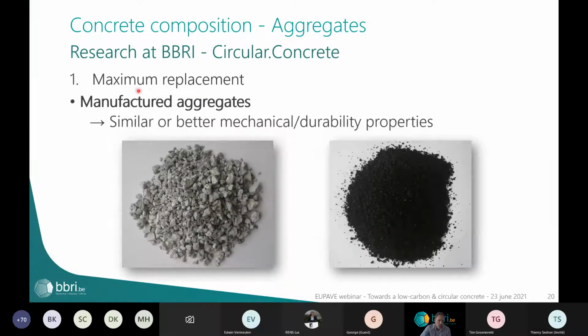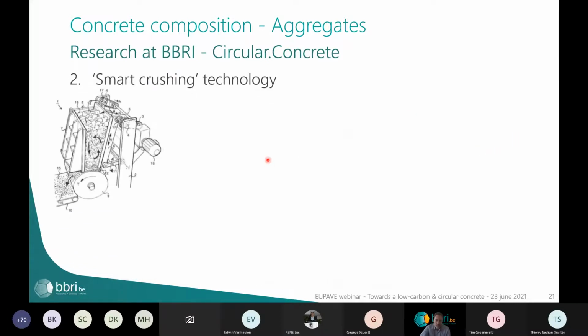So, and when we look, however, at the manufactured aggregates, there in the high replacement percentages that we used, 20 to 50% of these aggregates that replace the natural sand in the concrete, we could not see a lot of influence on the mechanical and durability properties, and we even saw on some aspects a better, a good influence of the usage of these aggregates. So this is a very important result of this limited scale